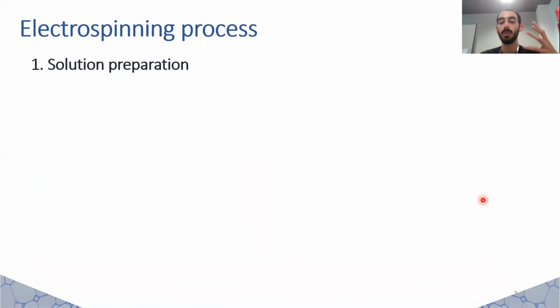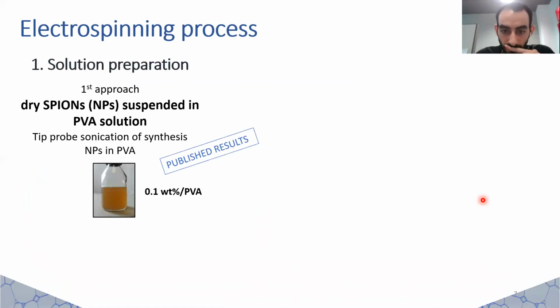We prepared electrospinning solutions using two approaches. In the first approach, we suspended previously synthesized and dried nanoparticles in a PVA solution using a tip probe sonicator. The final nanoparticle concentration achieved was 0.1% with respect to PVA. The results obtained by this method were published last year.